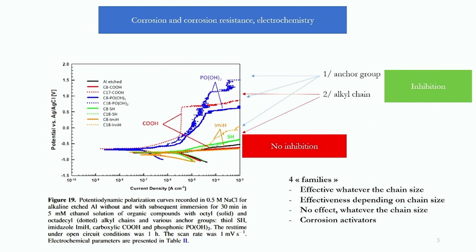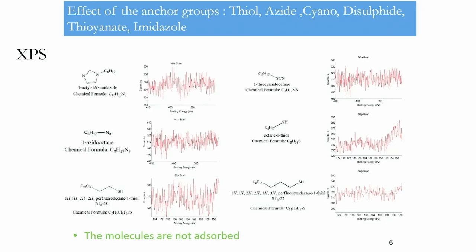We did systematic surface analysis. The molecules that have no effect on corrosion inhibition are those that absolutely do not adsorb. The XPS results show that for the fingerprint element of the molecule, there is nothing — no adsorption, no inhibition.